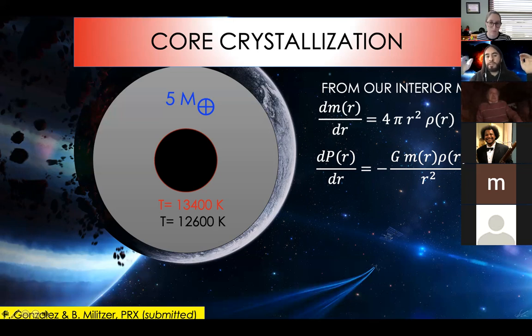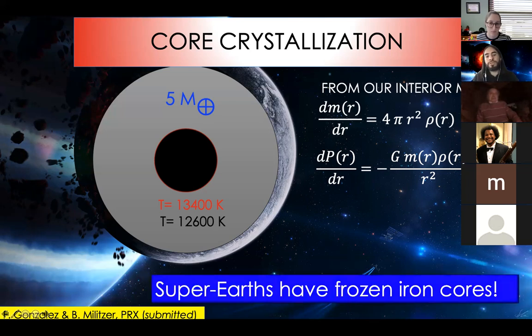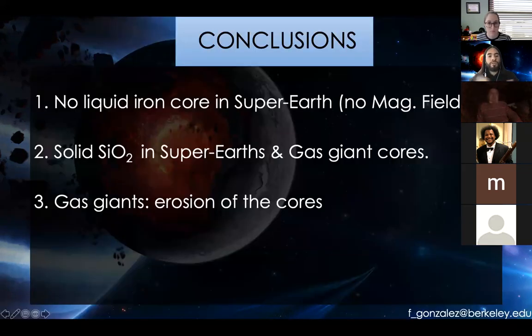So it means if the temperatures at the interior of a super Earth are below the temperature that is necessary to crystallize the entire core, it means that super Earths have frozen cores. They cannot produce an outer core that is liquid like we have on the Earth, because the pressure is so high in these planets that it crystallizes iron at the center. So if this happens, it means that we won't have this interaction between an inner core and outer core that, through convection, generate a magnetic field. So it is possible that super Earths cannot have a geodynamo that generates a magnetic field. But remember, they can still generate magnetic fields from their mantle using the silicate liquids.